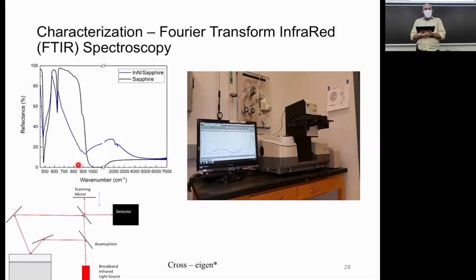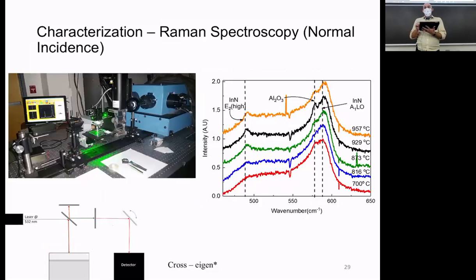Because the crystal is a wurtzite-type structure, some of these features here, so you can see this is just our sapphire curve up the top here, some of these features that are in sapphire get changed up because of the indium nitride, and they're absorbed differently because of the indium nitride. And we also have some other features down here that are interesting. So these things all play a factor in how we understand how this material is behaving.